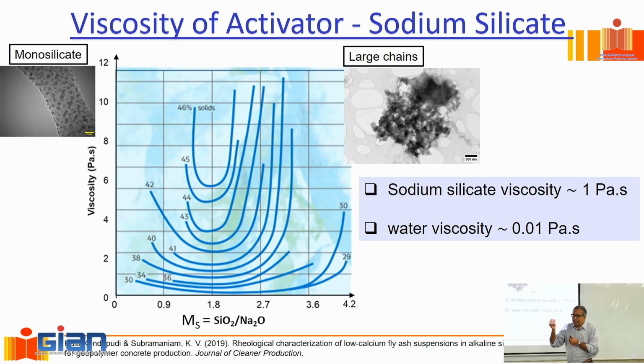And so you need something that structures very quickly. How do I measure that? Thixotropy. I measure the thixotropic buildup that's available. There are standard protocols for thixotropic buildup, and of course, modifications have been made for the measurements. The most common measure is what I showed you as SRE, right? So what are you doing there? You're measuring the energy it takes to break the structure. Not the initial structure, but the structure after you've sheared it off. You shear it off, you let it come to rest for different intervals of time, and then you measure how much structuration has happened. The more structuration that happens after shearing off and the rest period, the higher the energy required to shear it off.